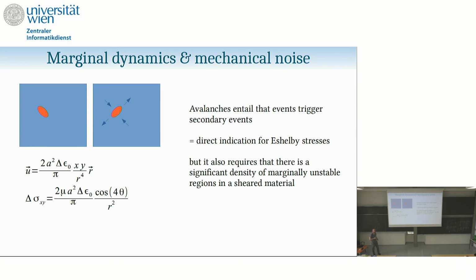So it also means that for that to be at work, you need a reasonable number of these regions which are very close to threshold. Because if it's extremely rare, then your stress field will not trigger a secondary event. It can trigger secondary events because you have other zones which are arbitrarily close to the threshold. And why is that? Well, simply because you shear. If you're in steady state shearing, you're constantly driving the system towards these instabilities. You have one instability that triggers a plastic event, but all the regions of your system are progressively driven towards instability.